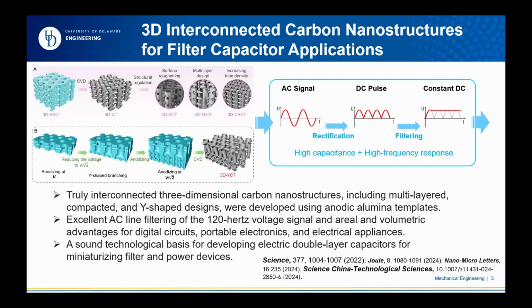First, just a simple structure, and we also do some surface modification, roughening the surface to increase the surface area and thereby the capacitance. We also make multiple layers, like Russian toys, so multiple toys. You have multiple layers, and you can also increase the density of this structure by tuning the template: increase the structure density, decrease the diameter, and decrease the distance between structures. Just recently, we also applied this to make a Y-shaped type of three-dimensional structure. All the papers were published recently. This is what we call the supercapacitor application for filter capacitors.